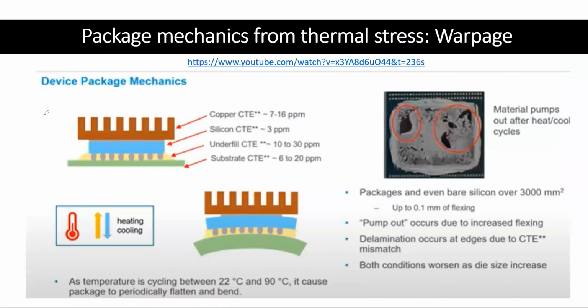If you recall what I mentioned last time, the thermal stress can induce warpage. Because of the thermal history, the residual stress, and the heating and cooling, eventually you will have bowing. And this bowing could actually make material pump out. In this case, the glue in between, adhering the two pieces together, because of this bowing and unbowing, this heating and cooling cycle, eventually acts as a pump to pump the material out. At the end of the day, it could fail like this.